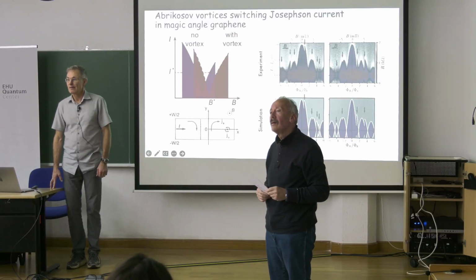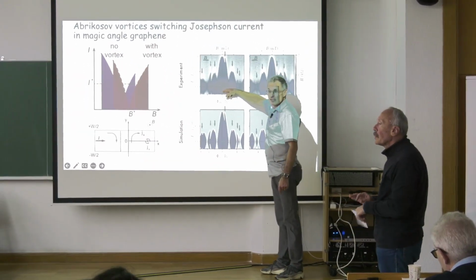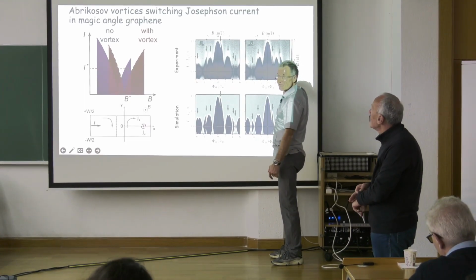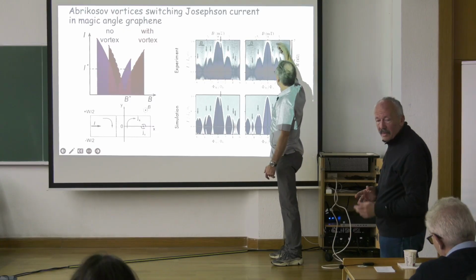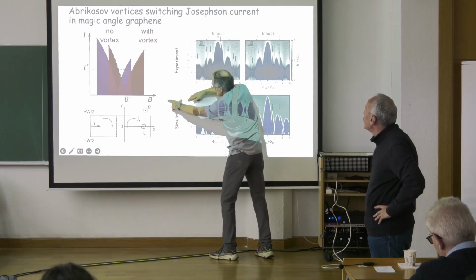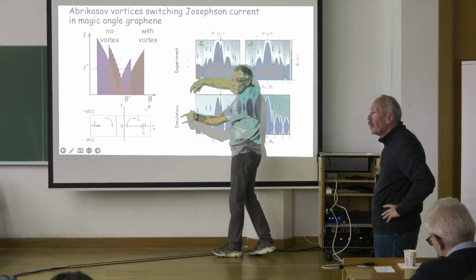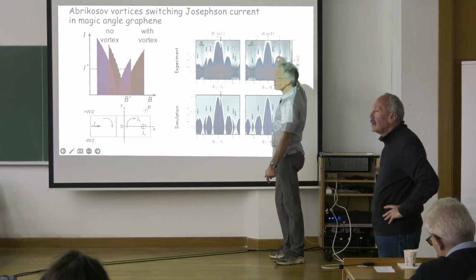Regarding that figure, the upper one, you have resistivity as a function of the applied magnetic field. It's magnetic field and intensity. That's current on the axis, okay. That's magnetic field, okay. And color is differential resistivity. Dark blue is low resistivity, white is high resistivity, because the IV curve looks like this, and then there's a steep rise. When it's a steep rise, you have high differential resistivity, and then it's less.